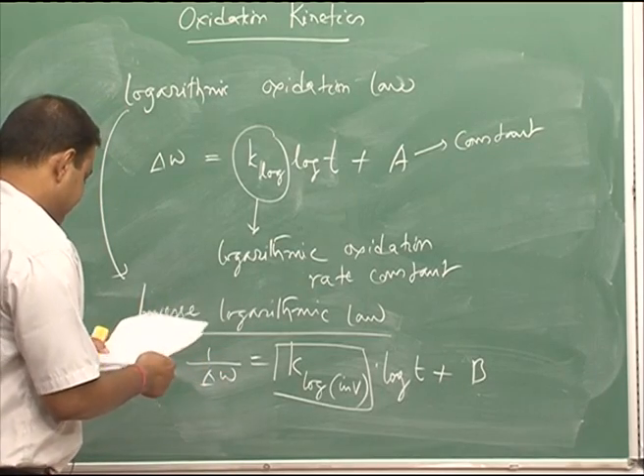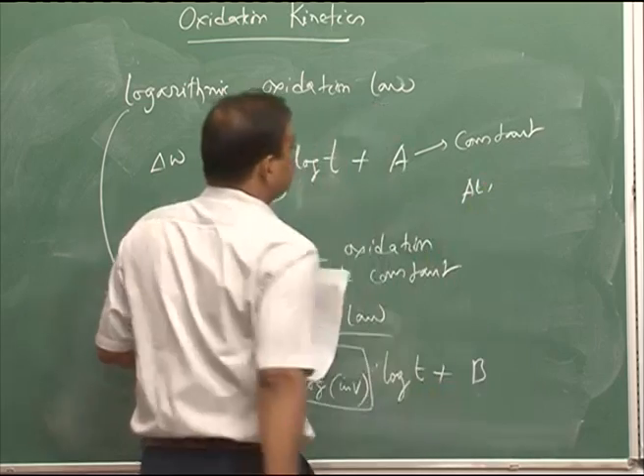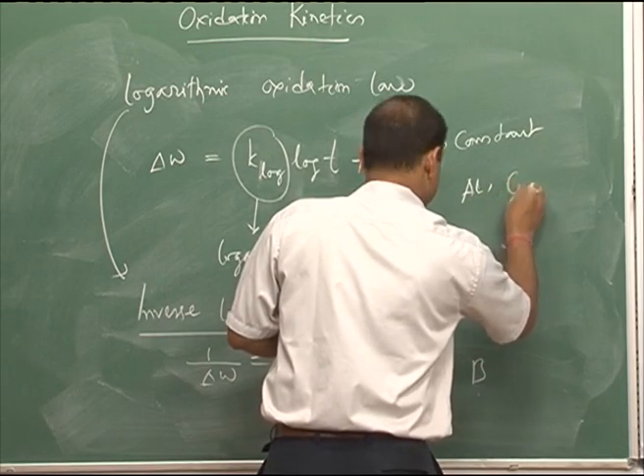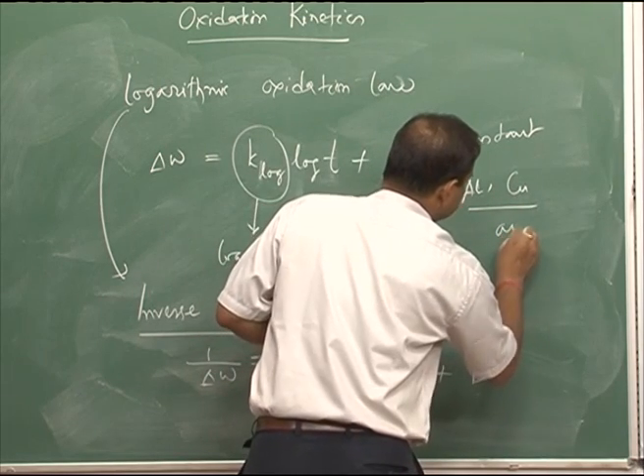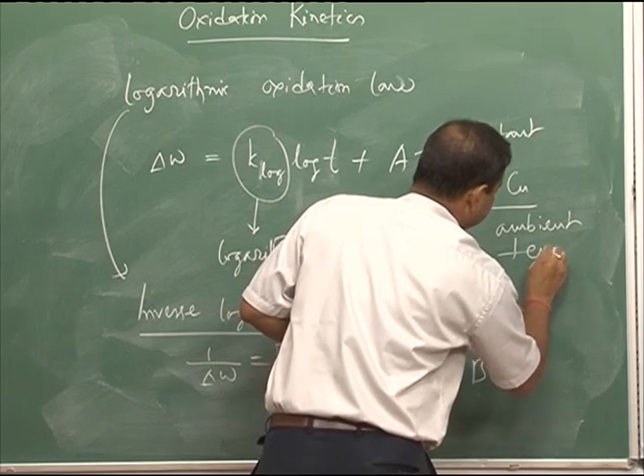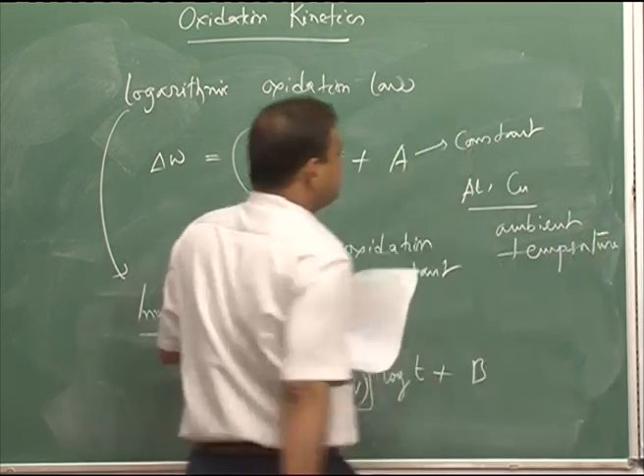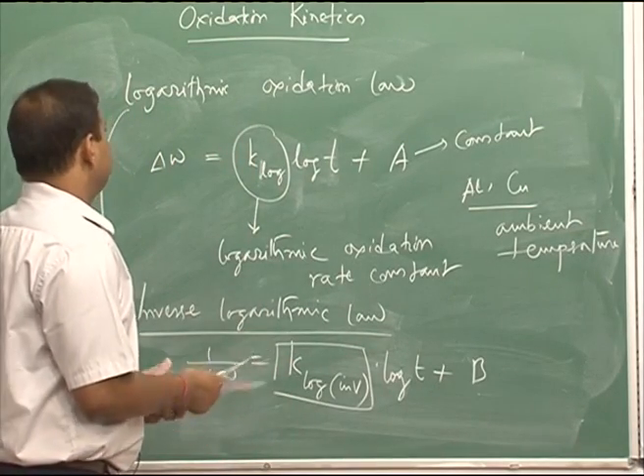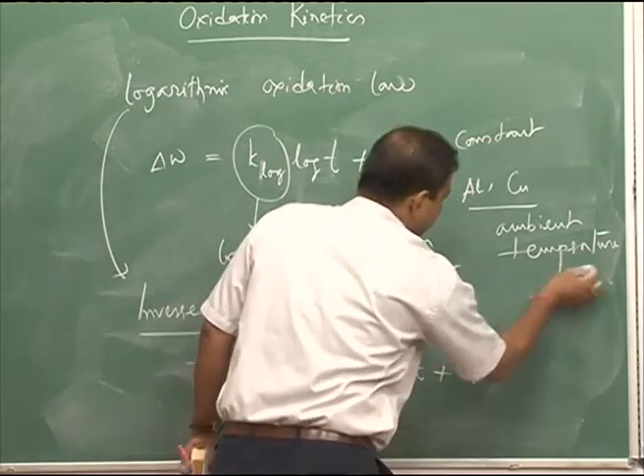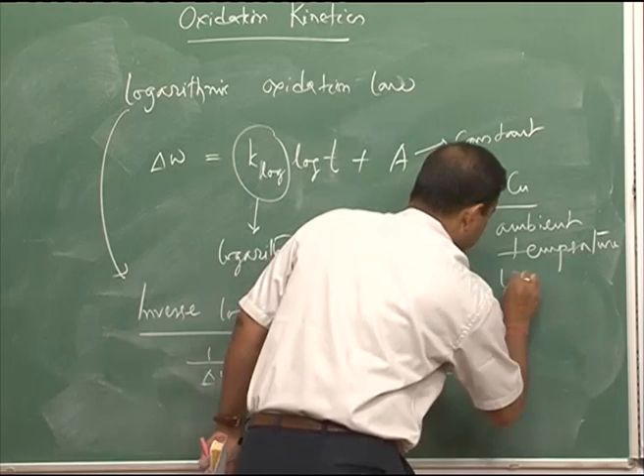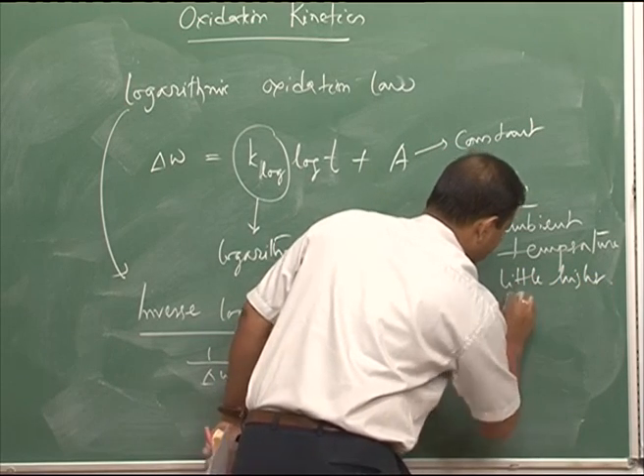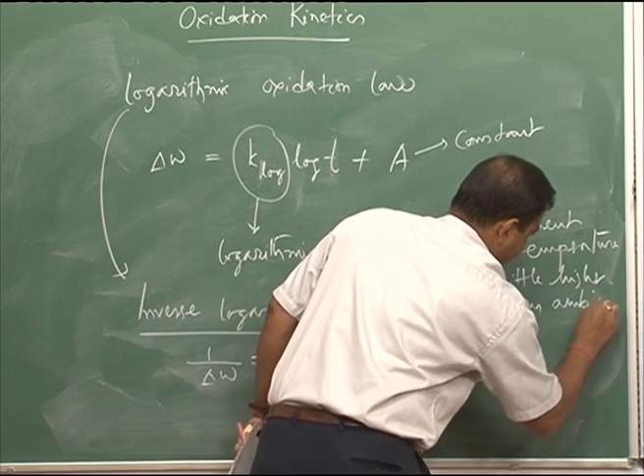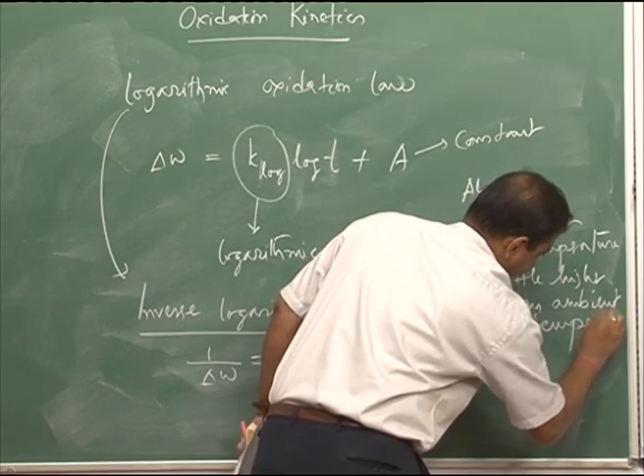And the example is, for example, aluminum and copper at ambient temperature. They would follow this logarithmic oxidation law, at ambient temperature or a little higher than ambient temperature. Now, we can also have one more law, that is called the cubic oxidation law in some cases.